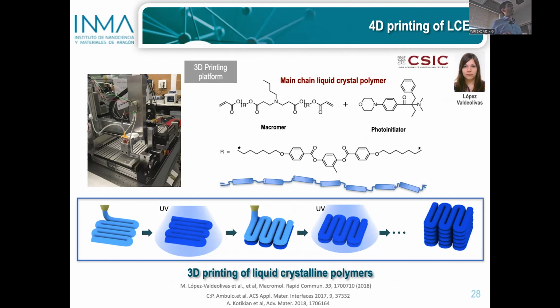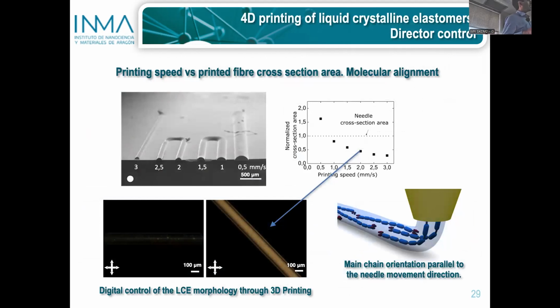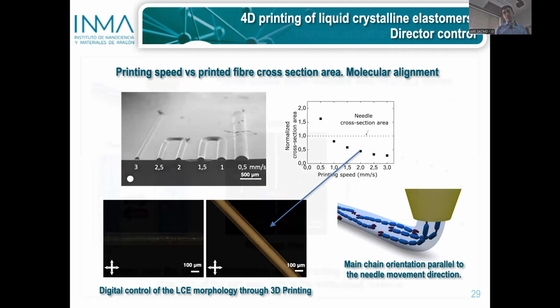And we can repeat this process many times and go to many layers, growing into the third dimension. Here you see lines of material printed at different speeds. We can see that the higher the speed, of course at a constant flow rate, the thinner the layers we get. Especially for the higher speeds, what we can check with polarization optical microscope and with dichroism measurements is that we get alignment of the molecules, as you see in the cartoon. So with this technology, we gain digital control of the director, digital control of the morphology of the material. We can control how the molecules are aligned during the printing process.